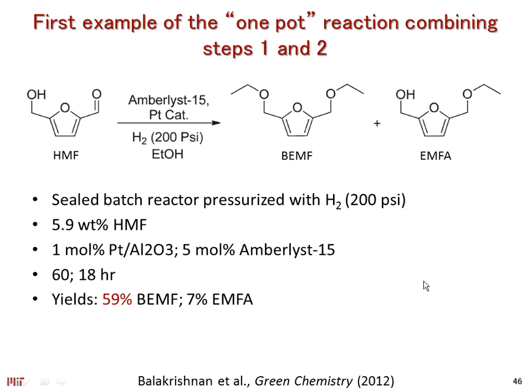But Professor Bell's group was probably the first one to show that you can actually couple these steps, starting from HMF. We know with Bronsted acid chemistry that you can do an etherification reaction with the hydroxyl group over there very easily. But if you want to make the diether, which is a preferable ether component as a fuel additive, you would have to hydrogenate then this carbonyl group into an alcohol and then do the etherification. That's where you have to couple, for example, a platinum-based catalyst with acidic resin, for example.